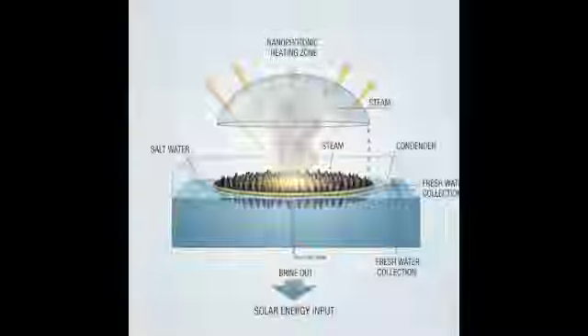Very promising. What about simpler methods like dip coating? Just dipping the membrane into a dispersion. Dip coating is straightforward and potentially scalable. You immerse the membrane in a solution or dispersion containing the photothermal material, and then control the withdrawal speed and drying conditions to form a thin layer.